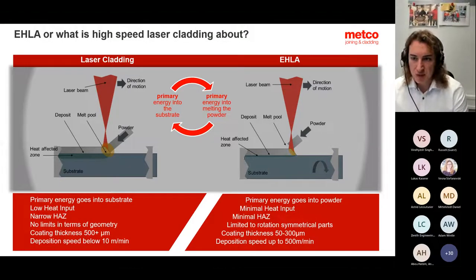Primarily, it started with rotation symmetrical bodies because it's easier to rotate certain cylinders. And then you get thin coatings. And under thin coatings, as I said, I mean something between 100 to 250 microns at extremely fast deposition velocities, which on a lab scale people try even up to 500 meters per minute. Typically, if you look also at the last training videos, for example for brake discs, the typical velocity is between 100 and 150 meters per minute, bringing you a really high quality coating on the surface. Also for this, you need special nozzles, which can guarantee a very smooth powder flow, and you also need a certain powder morphology, which we are going to look at together in the next slides.